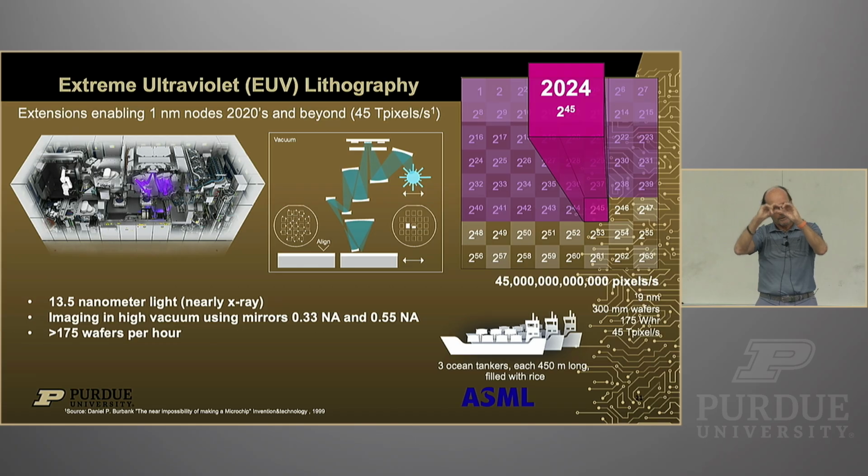If I make the thickness of all these layers exactly right, then this light, and this light, and this light all have the same phase, because the path length every time changes by one wavelength. So it became really, how can we make these multi-layers with exactly the right thickness so that I get this reflection? And ultimately now we can achieve about 70% reflection.